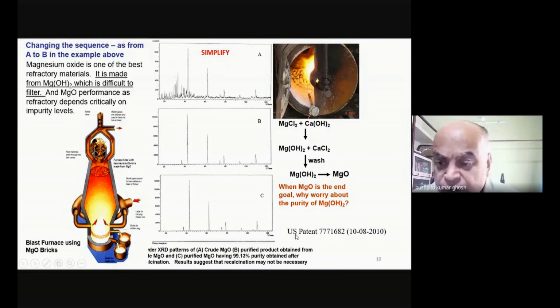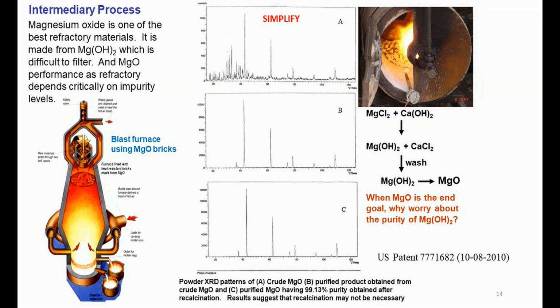You can see it was novel enough that these are all patented. And just to show you, this is the crude mass which has magnesium hydroxide, calcium chloride, maybe some unreacted lime also, I don't know. And when we calcined and washed it, we ended up making the purest product you can imagine in an extremely simple way. How did we do that? We changed the sequence. And of course, we focused on the intermediate.